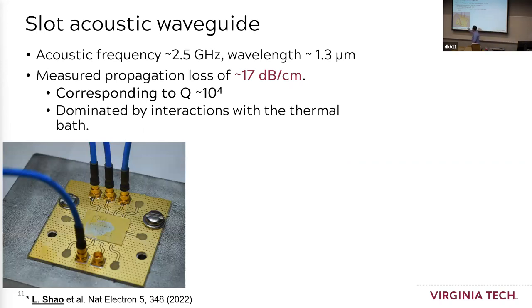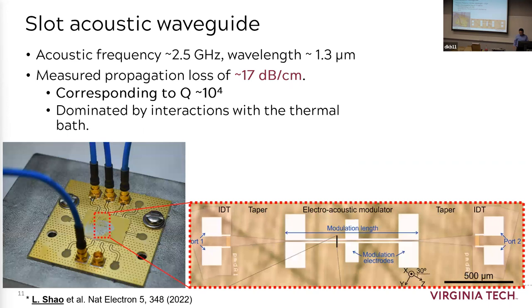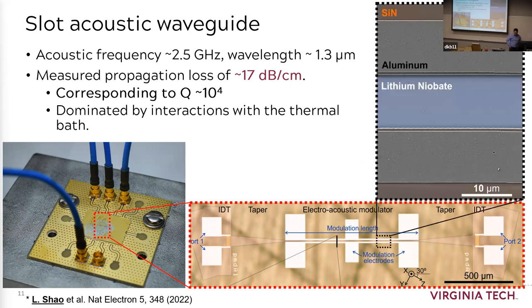The printed circuit board, this is another chip we made, and the lines on the top are actually the waveguides. And also with the modulators, I will do some modulators later. You see that's the waveguides we made. And this is the SEM. So this waveguide is excited by an acoustic wave at about 2.5 gigahertz. And we measure the loss at about 17 dB per centimeter.